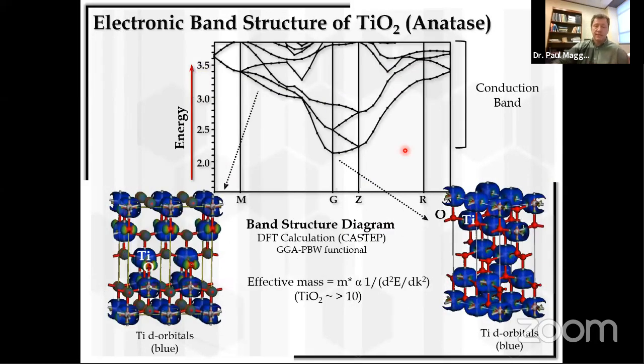You can take a look at this by DFT calculations and you find consistent results as well. And so here I'm plotting energy versus K space for TiO2, its anatase polymorph. And in particular, I'm showing you the conduction band. And so this G is the gamma point. And as I described, at the gamma point in K space, as we see as the result of DFT calculations, we have titanium d orbitals that are non-bonding. There's no overlap between the electron density on the titanium here and any electron density on the oxygen. But then as you go away from the gamma point in K space, this band disperses up very fast in energy.